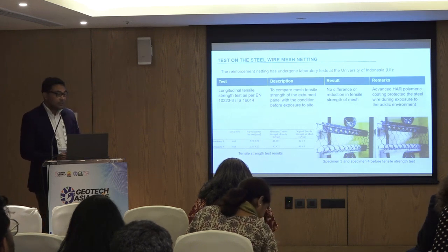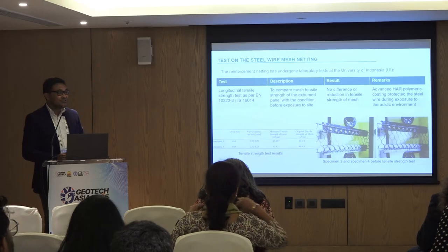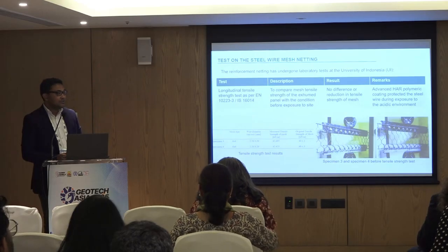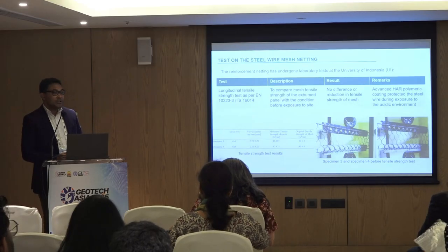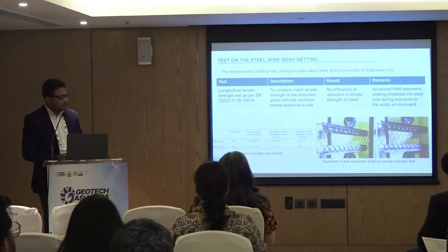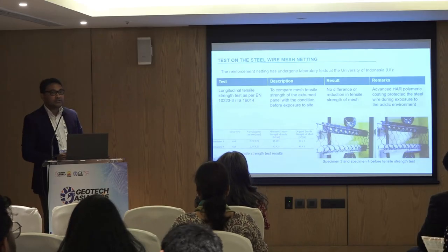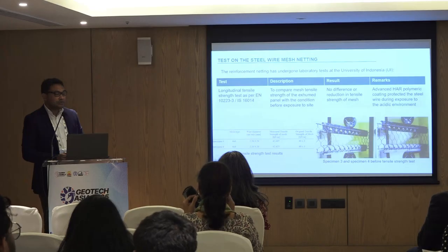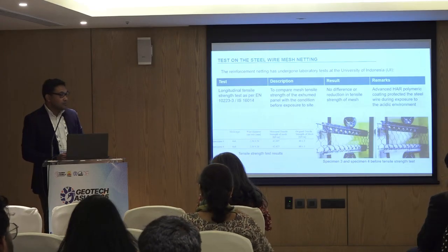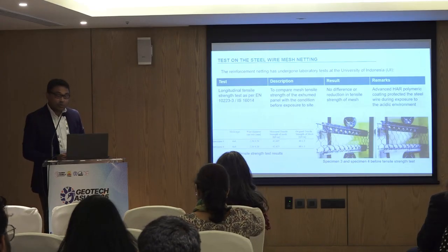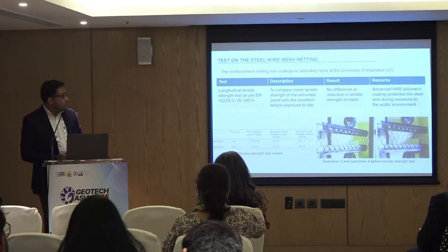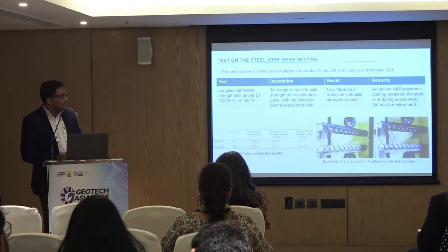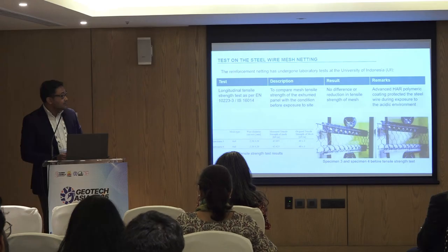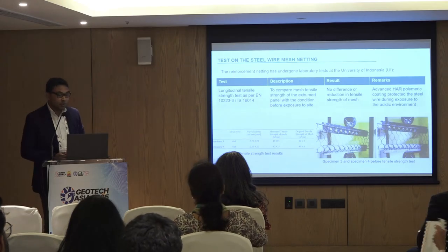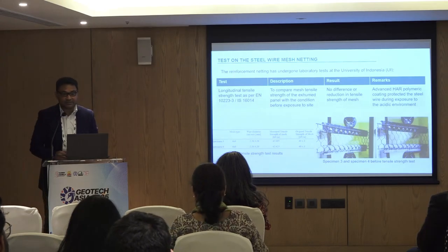And we checked the longitudinal tensile strength, and we found that the results from the exhumed material are in line with the value record that we have for the fresh material. So what we can see is that there is no difference or reduction in tensile strength thanks to this coating that has protected the steel wire.